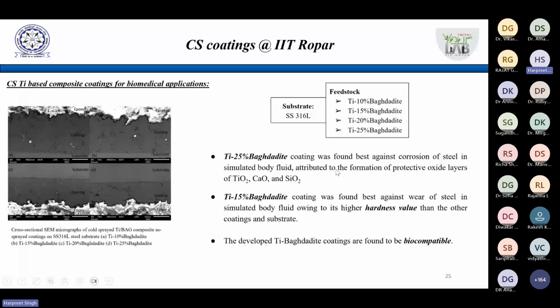So you can see different types of materials have been deposited. This is some work which we have done at IIT Ropar also. And this is about depositing titanium and Baghdadite coatings, right? So Baghdadite is a promising material which can replace our most commonly used material, hydroxyapatite, which resembles our bone. But the problem with HAP is that it has lesser mechanical strength. So by chance, Baghdadite also matches very much with HAP as well as bone material, because it's again calcium based, but it has some zirconium which makes it mechanically better also.